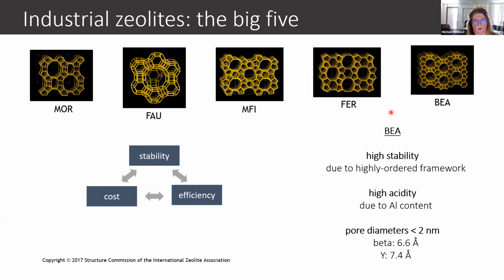So I'm going to talk a little bit more about beta zeolite. And the reason why this one is of interest in the oil and gas area is because it's highly stable, and that's because of its highly ordered framework. It has very high acidity, which is due to its aluminum content, and it also has a pore diameter of less than 2 nanometers.